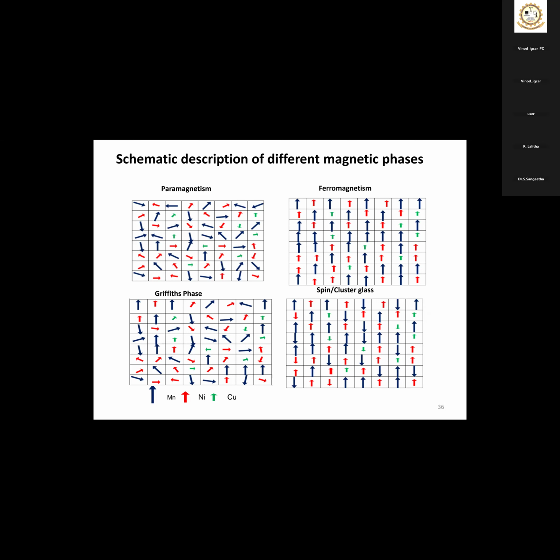Actually, why this happens is related to that earlier slide I was explaining, ordered versus disordered. Depending on the disorder, you will get a local short range ferromagnetic order or paramagnetic disorder, that kind of thing. Because of that, you will get a Griffiths phase. And in the last end compound, you get a spin or cluster glass.